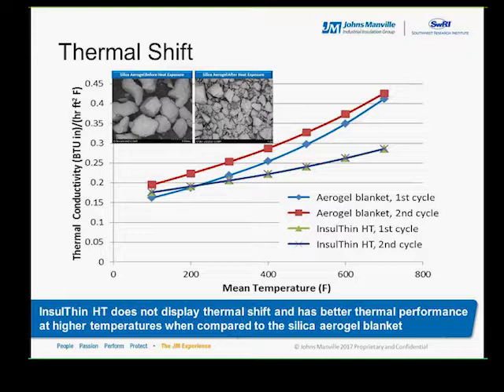And this can be seen in the difference between the two lines in the graph comparing the first and the second cycles on the graph on this slide. The first cycle is data from virgin product not exposed to heat, and the second cycle is a repeat of the same material exposed to a mean temperature of about 700 degrees Fahrenheit. The first and second cycle lines are right on top of each other for the insulation, meaning that the temperature does not really affect the thermal performance, but with the aerogel you can see 20 to 30% higher values on the second cycle compared to the first cycle.